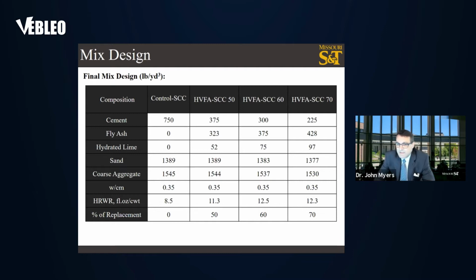The final mixes for the design of the high volume fly ash SCC are presented in this table. And as can be seen, the sand and coarse aggregate weights were adjusted to take into account the effects of the specific gravity of the cementitious materials. The control is the standard conventional self-consolidating concrete. And then we had a 50% high fly ash content, 60% fly ash content, as well as 70% fly ash content.